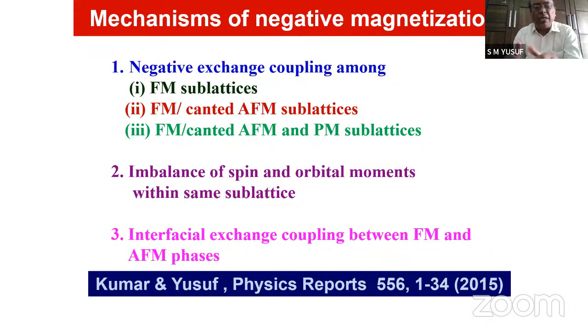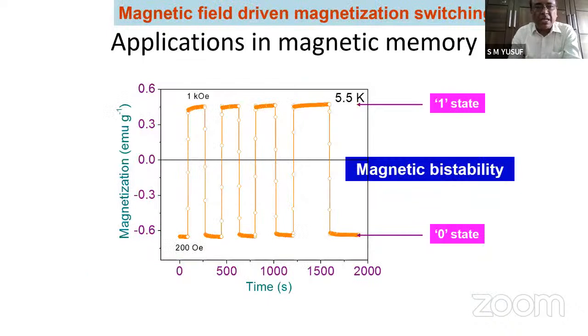But now we are going to real 2D thin film multilayer material by creating an interface in this material, and we are now working in this direction. So in all these cases, the exchange bias, magnetization reversal is expected. And as I said, when magnetization changes sign, here we have shown as a function of temperature that it goes from the negative side to the positive side.